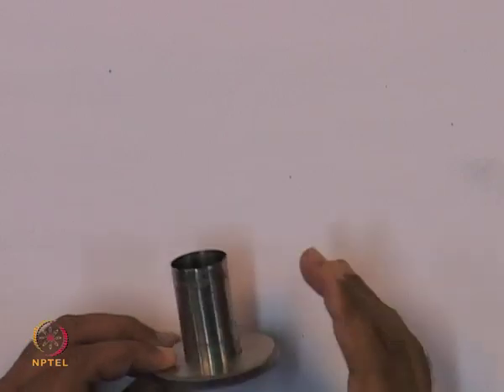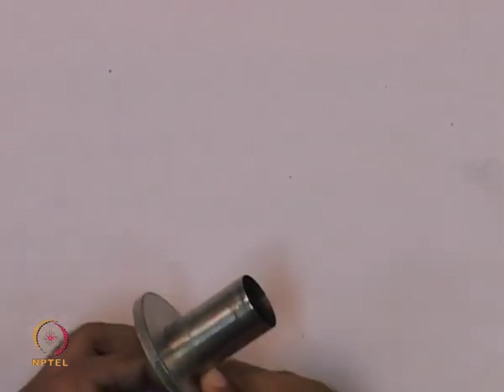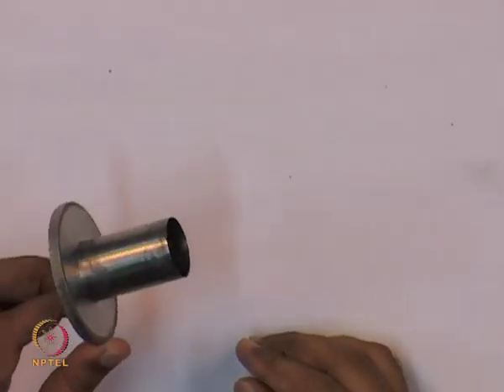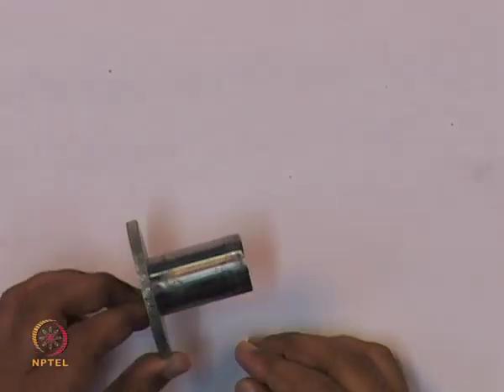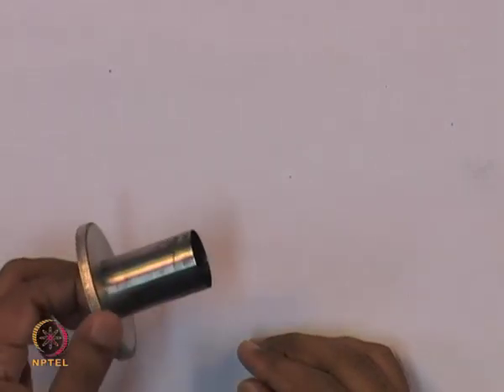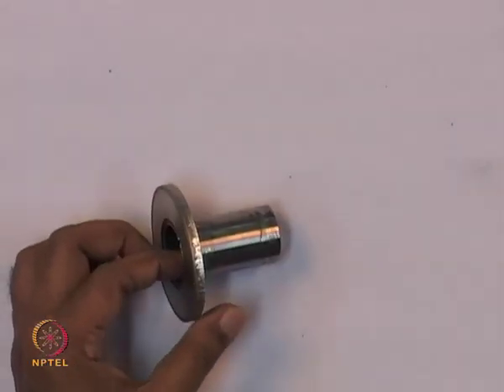One has to really calculate the hoop stress in this case and then calculate the dimensions, but a thickness of 0.15 to 0.2 millimeter or 0.3 millimeter can stand very high pressure. I just brought this specimen to show you that such a small thin walled tube can stand very high pressure. SS304 is the material being used for this particular purpose.